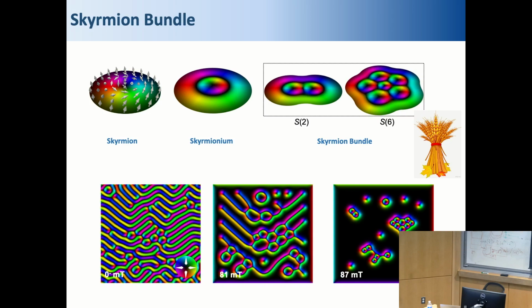Then we gradually turn on a positive field. But these skyrmions with center spin up are not stable under a positive field. Most of them will be annihilated. But still there are some skyrmions that remain. And these skyrmions remain because they are wrapped by a helical lane. So this helical lane provided a bag to support the presence of these skyrmions inside. So this is a kind of non-equilibrium realization of the skyrmion bundle.